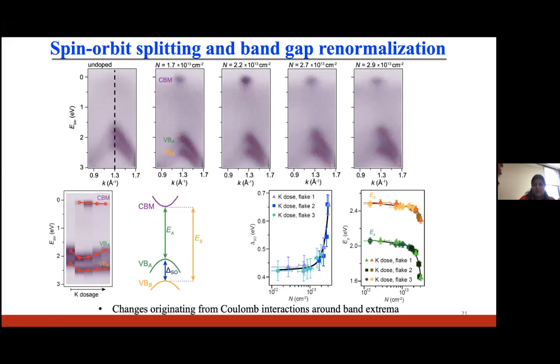On more and more dosage, we notice that the upper branch of the valence band shifts more as compared to the lower branch. This is what I'm showing in these two plots. Here we have the splitting as a function of dosage. In this range, with electron densities of 10^12 to 10^13, there is not much change to the spin-orbit splitting separation.